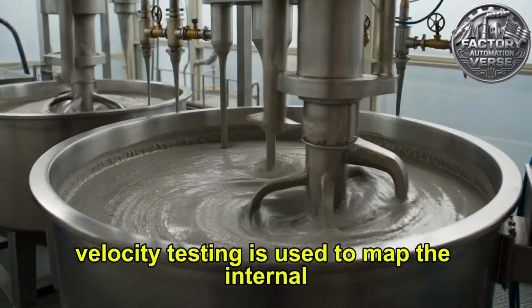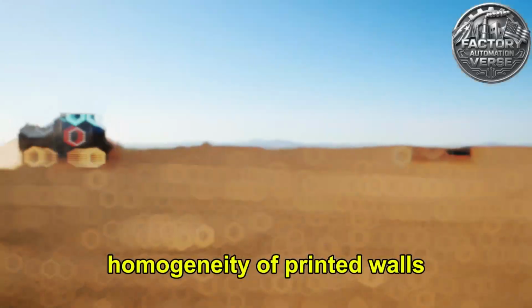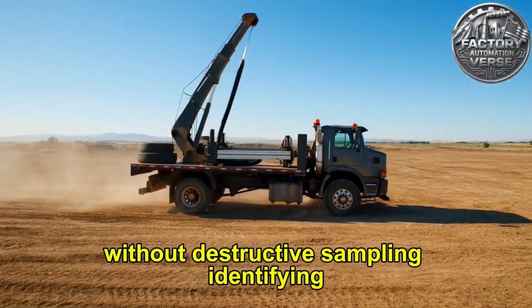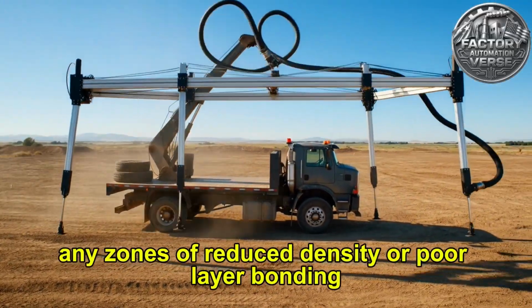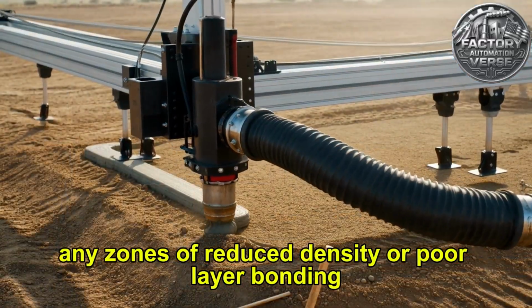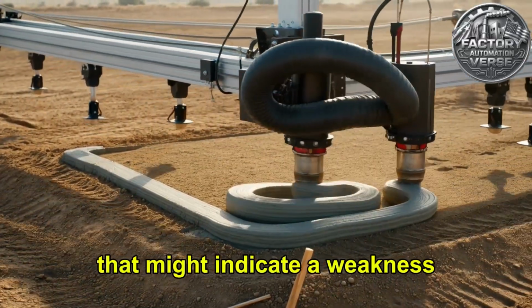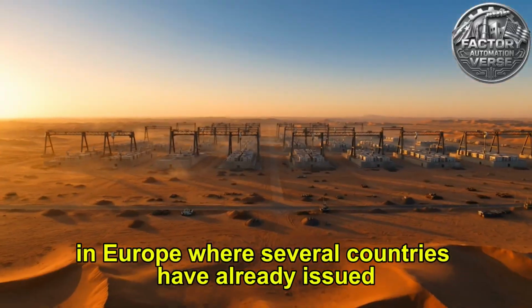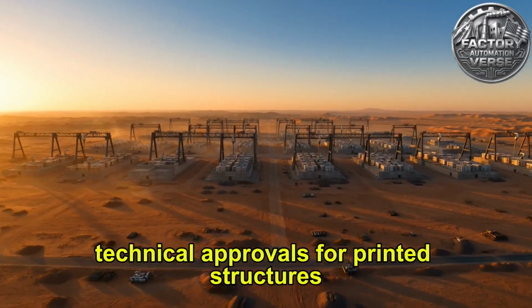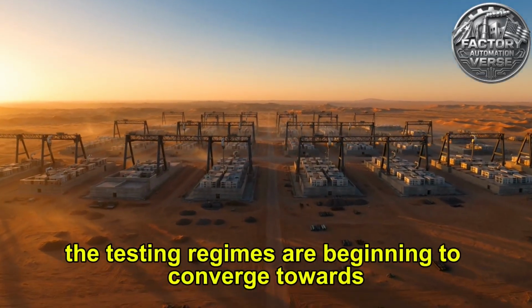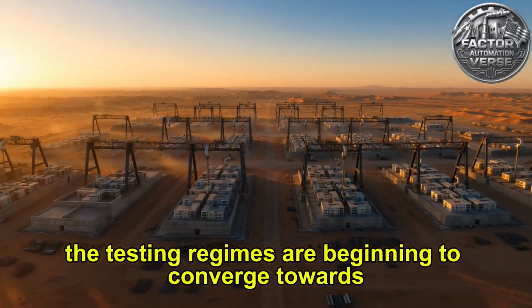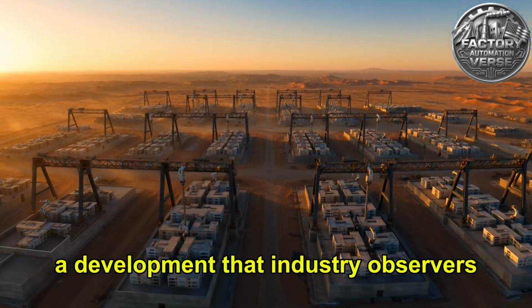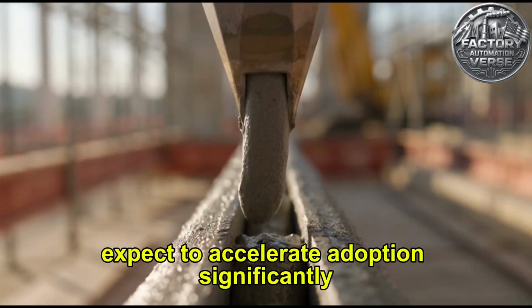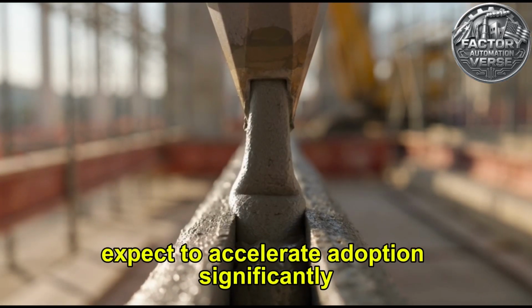Ultrasonic pulse velocity testing is used to map the internal homogeneity of printed walls without destructive sampling, identifying any zones of reduced density or poor layer bonding that might indicate a weakness. In Europe, where several countries have already issued technical approvals for printed structures, the testing regimes are beginning to converge towards standardized protocols, a development that industry observers expect to accelerate adoption significantly.